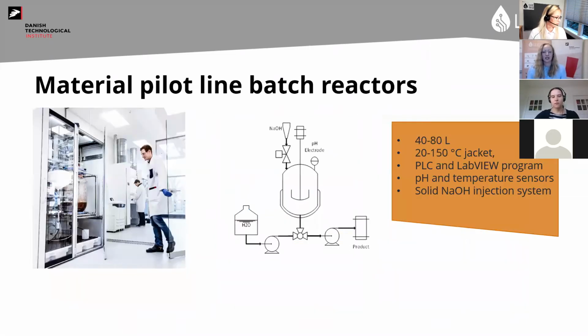So one of the pilot lines we have is the batch reactor line, and we have several, but this is just one of them. This is one of the big ones. It's a simple batch reactor in a way, but we have equipped it with a lot of sensors. You can have around 40 to 80 liters of liquid in it, and it can heat up from 20 degrees to 150 degrees. It is controlled by PLC and a LabVIEW program, and as I said, it has a lot of sensors. Among them are a pH and a temperature sensor, which are crucial for some of our synthesis. And then we also have an injection system, so we can add material during the process at a later stage.